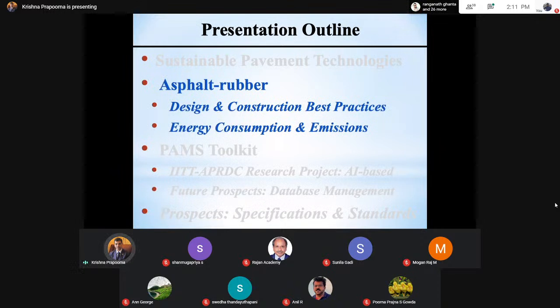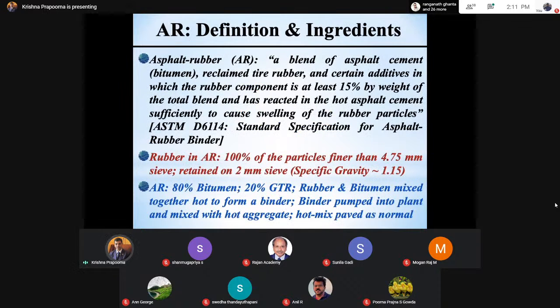Now coming to asphalt rubber as such, what is asphalt rubber? How do you define it? ASTM, the American Society for Testing and Materials International, is very clear that it is a blend of asphalt cement, or what we call bitumen, and crumb rubber inclusions, where the rubber content within this blend should be a minimum of 15% by weight of asphalt cement. Otherwise, you cannot call that blend asphalt rubber.